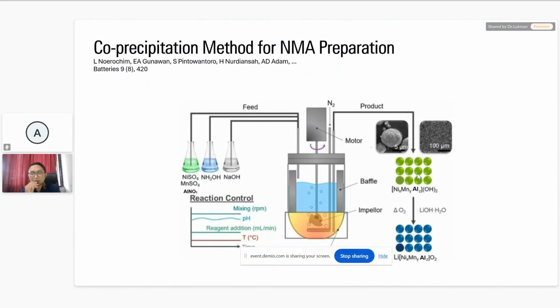In this method, we have to be very careful when setting up the apparatus, especially the nitrogen gas, which should be mixed well in the solution, because manganese and aluminum nitrate oxidize very easily. So if you prepare with this kind of method, make sure the nitrogen is mixed well by bubbling for some time in the reactor tank.